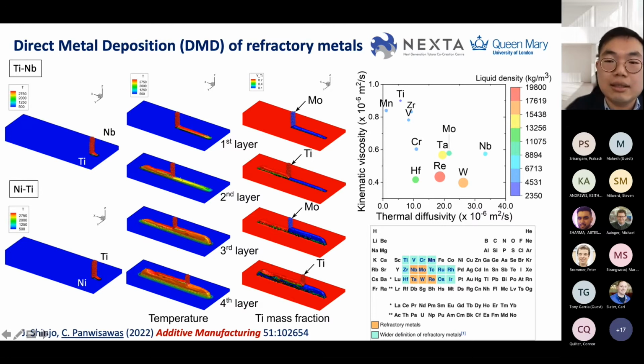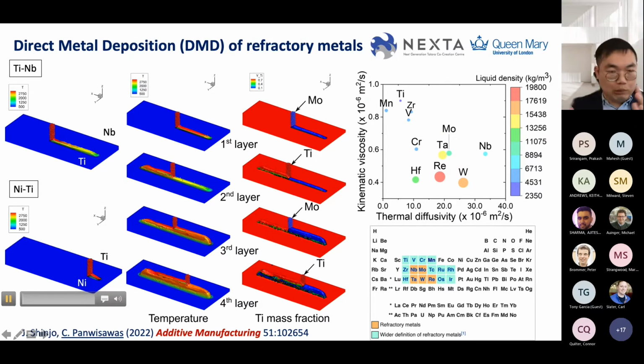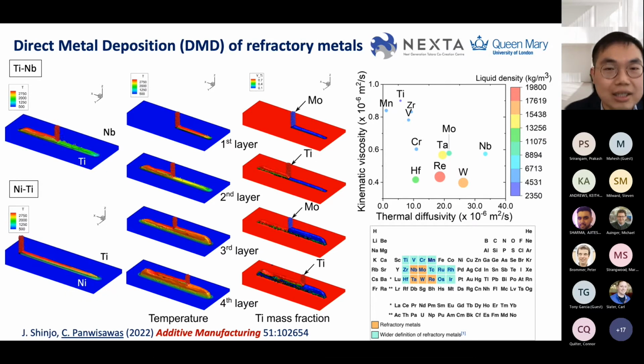And there is another process that I mentioned earlier, which is not part of it now. It is direct metal deposition, where you want to deposit different material on each other. For example, this one is kind of alternate titanium and a refractory metal deposition, where you have titanium niobium, for example, or titanium molybdenum pair. And our study here is to understand how the species actually mix together, and what is the barrier when you want to actually use this direct energy deposition to repair some component.